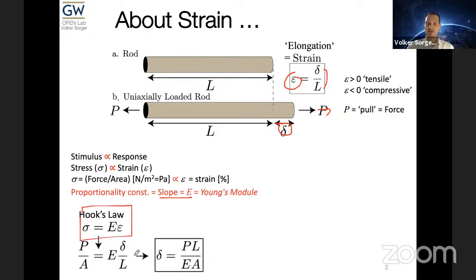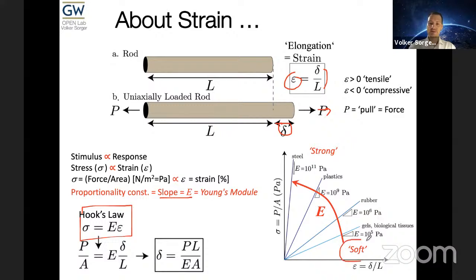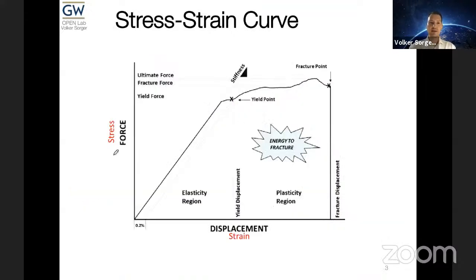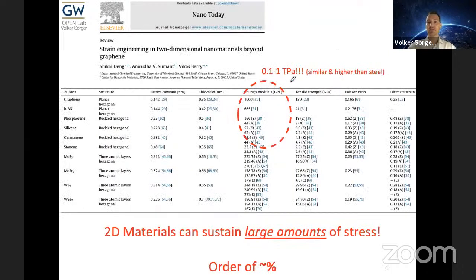That's basically what we show here: the amount of stress versus strain for various materials. We find these very soft materials, and then we find very strong materials. For instance, steel is one of the strongest materials out there. Turns out two-dimensional materials are even stronger, which suggests they could be very well used for straining. The stress versus the strain, in this Young's modulus regime, essentially is linear, but only up to a certain point, at which the material starts to yield or break and eventually fracture.